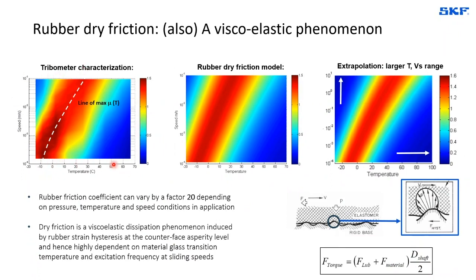So what we've been spending efforts on in SKF research and development is basically to understand this dry rubber friction. If you look here at the tribometer characterization, we are now able to replicate with our internal models the tribometer material signature when it comes to friction. And since we know that the dry rubber friction is also a viscoelastic phenomenon, coming from the excitation and the strain hysteresis response of the rubber against the counterface asperities, we are able to use the viscoelastic models that we have in order to extrapolate the behavior and the friction signature of our rubber for the dry part of the friction beyond what was characterized, allowing us to simulate and to predict in our virtual seals beyond what was indeed characterized initially.